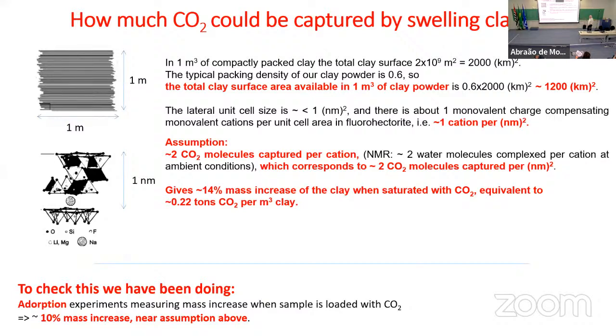So now imagine that these clay cards can capture CO2. The materials used for, say, capturing gases are porous materials. The porosity of the clay is very compact. It's a very compact system. If you imagine that you have 1 meter by 1 meter by 1 meter, 1 cubic meter of compact clay material, that actually contains 2,000 square kilometers of surface area. If you have a powder with a packing density of 0.6, it reduces to 1,200 square kilometers, but it's still a large area.